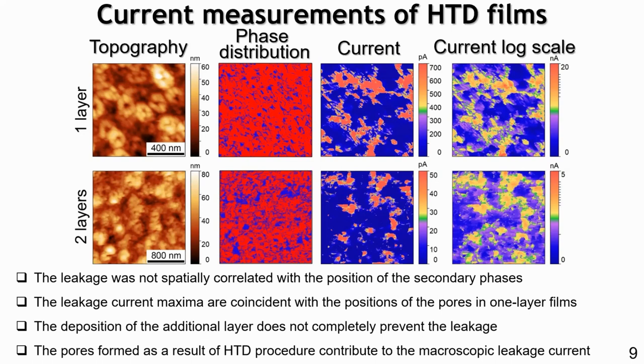operate as a really enhanced leakage current path, and actually these pores really hamper the properties of the material, so they reduce effective piezoelectric properties both in the sense of leakage current and in the sense of the piezoelectric response.